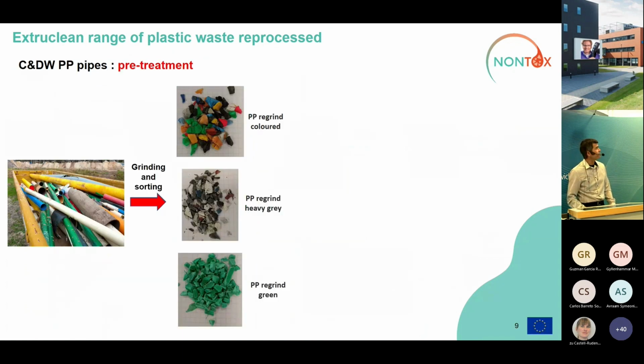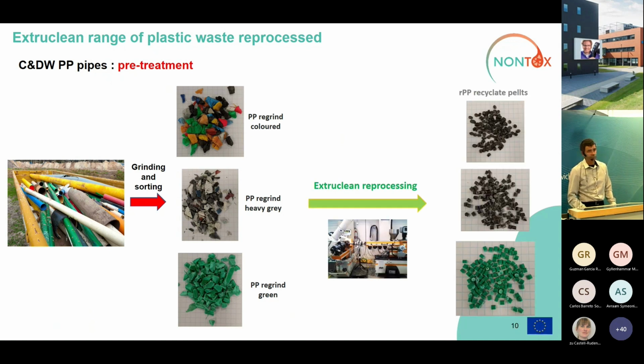Another type of waste consisted of construction and demolition polypropylene pipes. In the same way, we proceeded with treatment stages consisting mainly of grinding and sorting of different types of polypropylene pipe waste according to color and composition. Also performing the Extruclean reprocessing, we were able to obtain, in this case, polypropylene recyclate pellets with low VOC content.